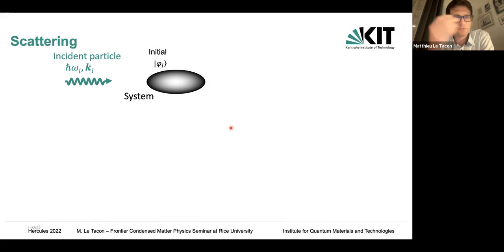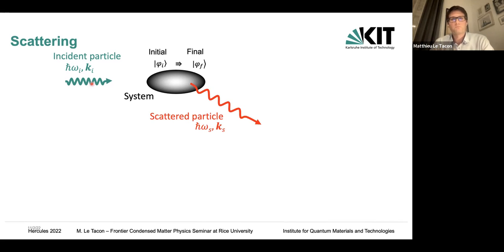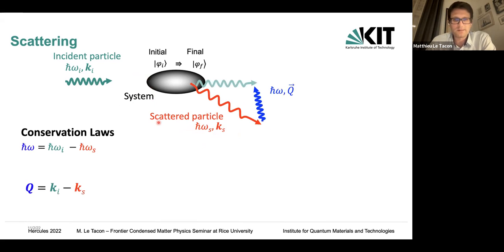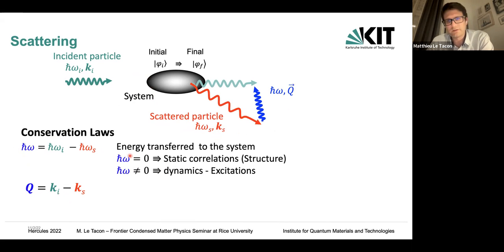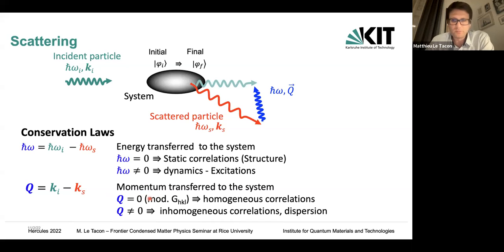I'm doing mostly scattering methods. Most people here are probably familiar with it, but just in case, what we do is we take some incident particles, typically photons, and we shine them onto an interesting system, which we bring from an initial to a final state. During the scattering process, the particle changes direction, so its momentum, and its energy eventually. So we have a scattering triangle and conservation laws: we have to conserve the energy and the momentum. Depending on the energy transfer we look at, we can investigate static correlations, which is pretty much what we do in a diffraction experiment, or the dynamics at finite energy. At zero momentum transfer, we probe homogeneous correlations, and at non-zero Q, inhomogeneous correlations, otherwise, as I said, the dispersion of the excitations.